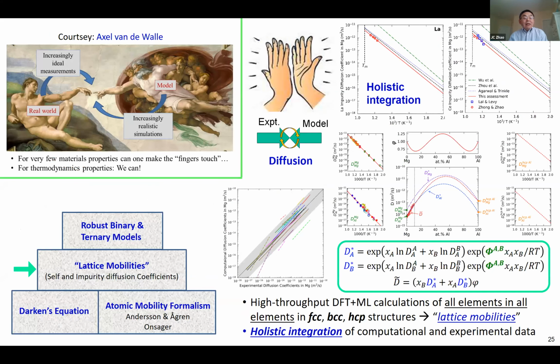So the other day, Axel van de Walle was saying that for thermodynamic properties, the computation and the experimental folks are almost finger touching in this case. I argue that for the diffusion coefficient, we are almost in a high five state. The agreement between experiment and modeling has become very impressive, and we can actually take advantage of both of them, and that's what I call a holistic integration.